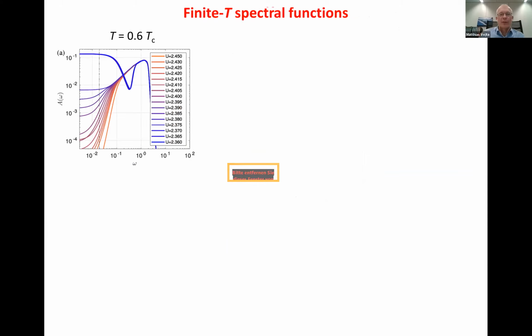So that was zero temperature. We have a regime of power laws at the point where this is expected, and then we can follow these power laws to finite temperatures. We simulate the same problem at finite temperatures, and what you see now is a temperature below that of the critical endpoint. You still see these very nice power laws, with spectral function as a function of frequency on a log-log plot.